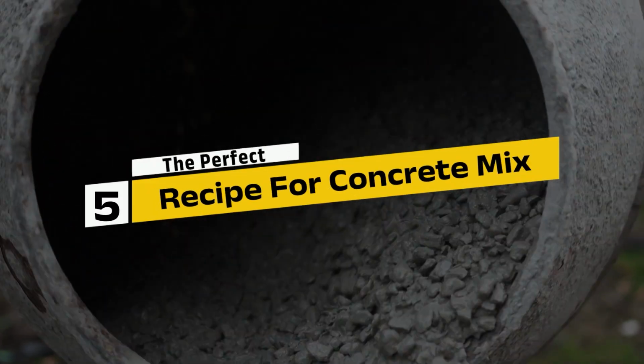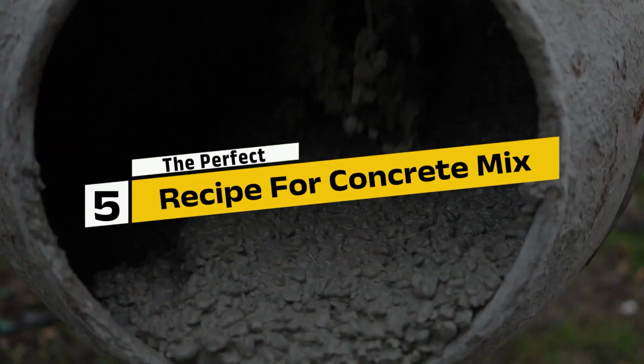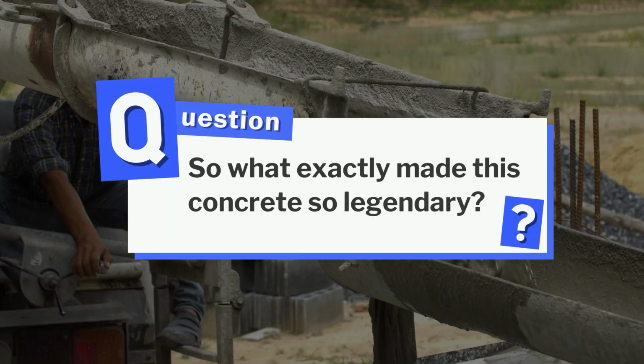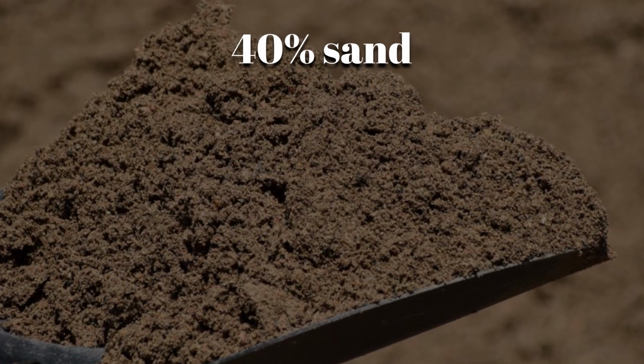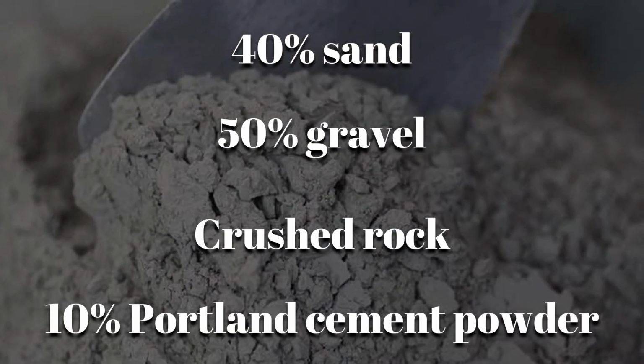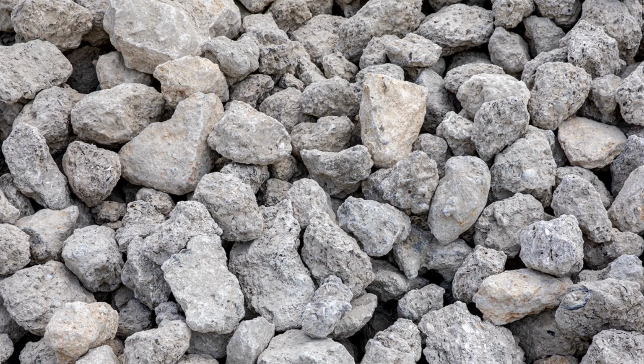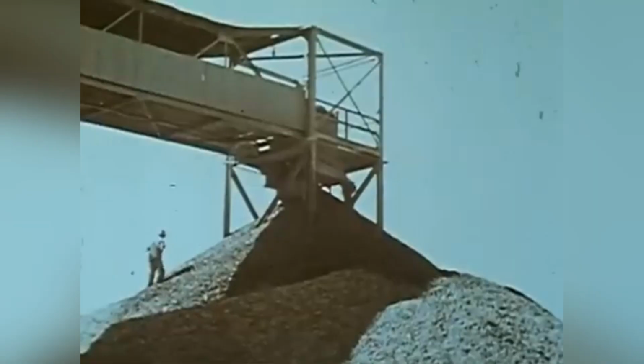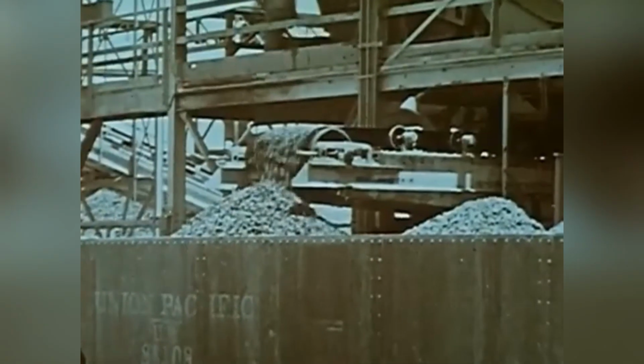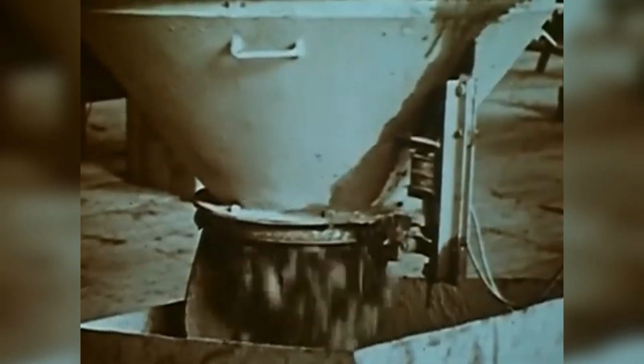Step 5. The perfect recipe for concrete mix. So, what exactly made this concrete so legendary? The recipe was deceptively simple but precisely calculated. The mix contained roughly 40% sand, 50% gravel, crushed rock, and 10% Portland cement powder. But the real secret lay in the size of the aggregate. Engineers used extra-large stones, some measuring up to 9 inches across, to reduce the amount of cement needed per cubic yard. This not only kept the mix strong, but also helped minimize the heat produced during curing.